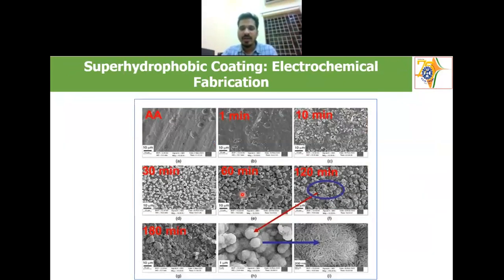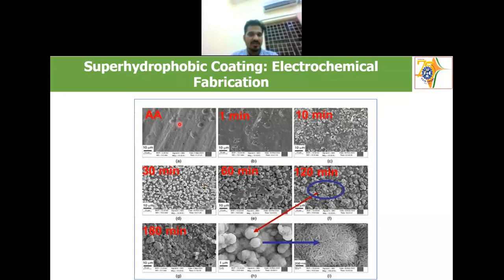So when we look at the FE-SEM images, there is the anodized aluminum surface image. Within 1 minute, we see that some kind of nucleation is happening, but there is no growth of the layer. Then at 10 minutes, in some areas it started growing, but there is no proper structure here, and there are many places uncovered.